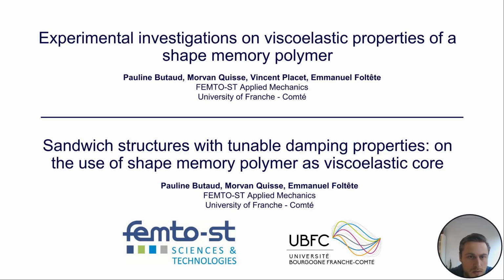The first one we'll talk about is the experimental investigations on viscoelastic properties of a shape memory polymer. What they did with this paper was set up really nice DMA experiments and were thoughtful in measuring the viscoelastic properties of a sandwich structure, using time temperature superposition and acknowledging the limitations of it.